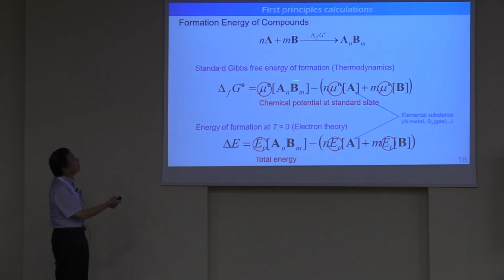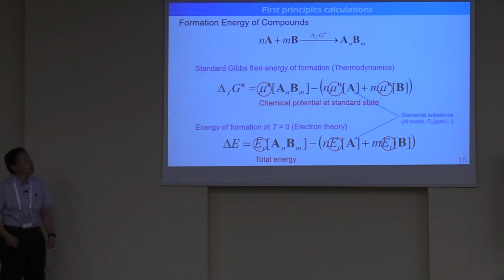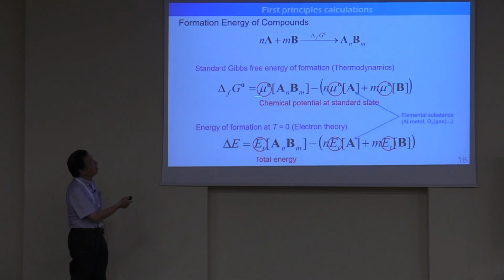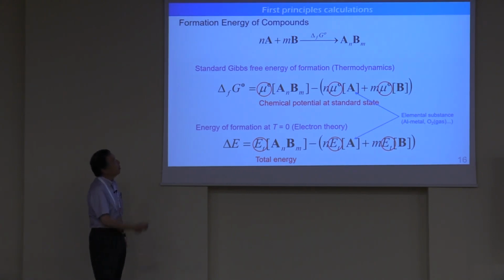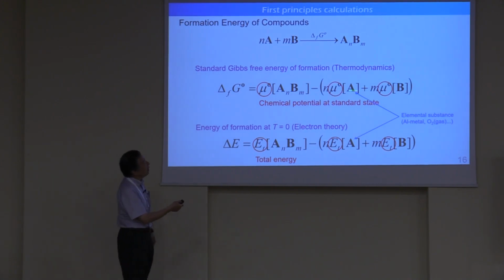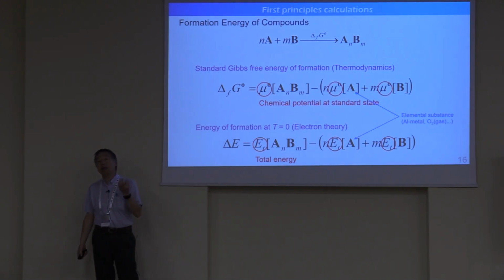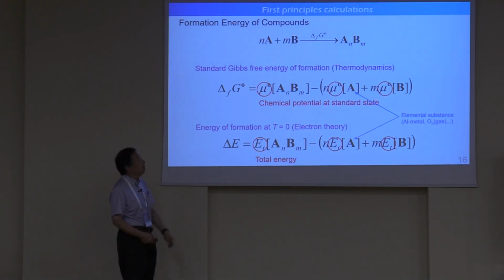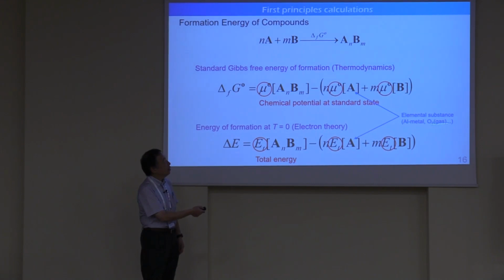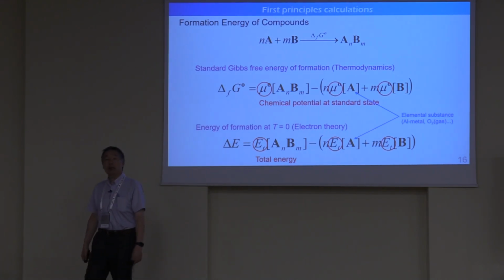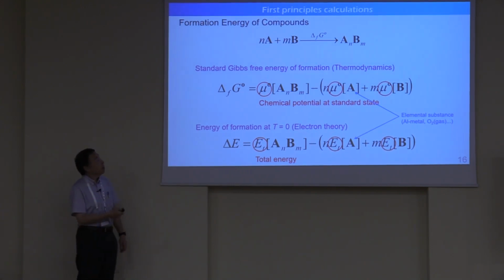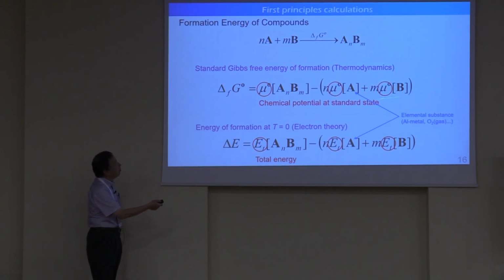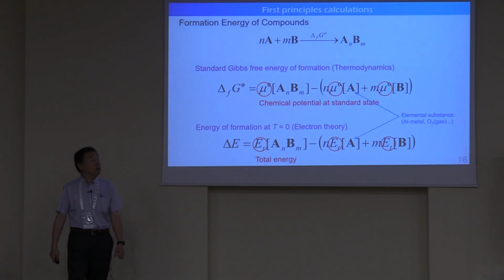The standard Gibbs free energy of formation in thermodynamics is expressed with this equation with the chemical potential as standard state shown here. And the standard state means this A is not atomic element A, but if it is aluminum, it corresponds to the aluminum metal. If it is oxygen, then it corresponds to the O2 gas. It is a standard state, often used in chemical thermodynamics. So in that way, experimentally people can define the Gibbs energy of formation.